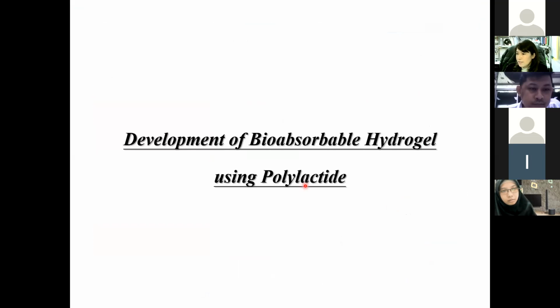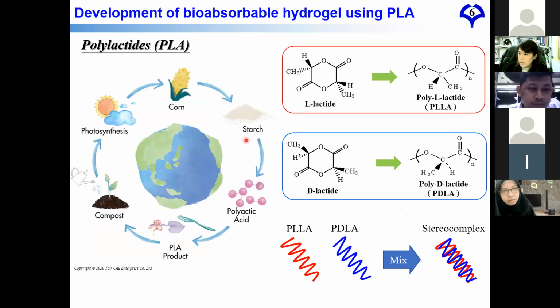So first is about the PLA hydrogel. We know that PLA is a carbon neutral polymer. And it's also very important that PLA has two kinds of enantiomer polymer, the L-lactic acid and the D-lactic acid. These two kinds, PLLA and PDLA, form reversed helices. So after they are mixed together, they combine and form the stereocomplex like this one.